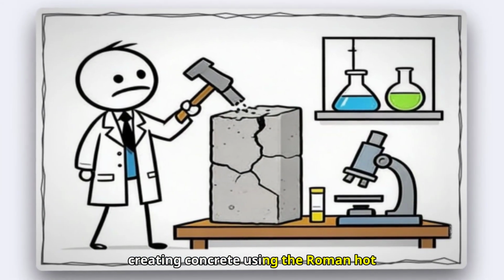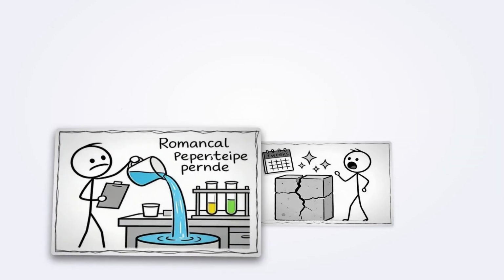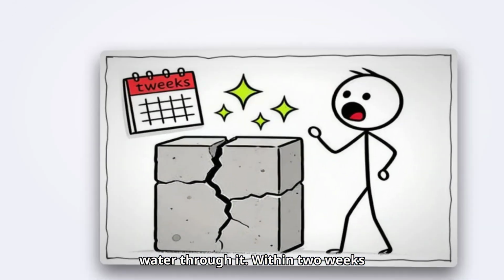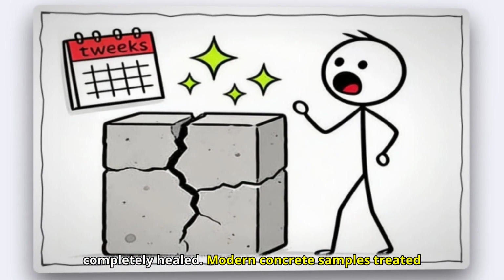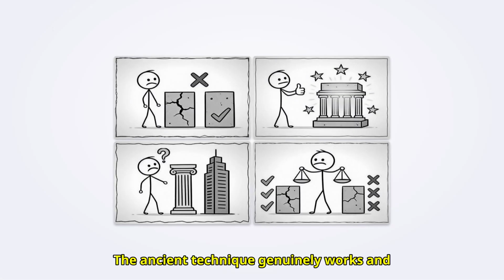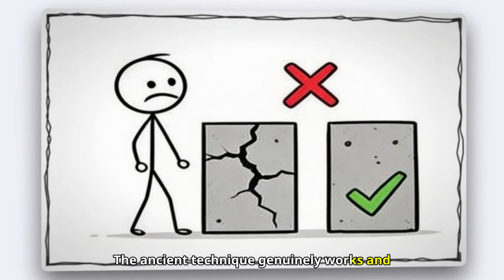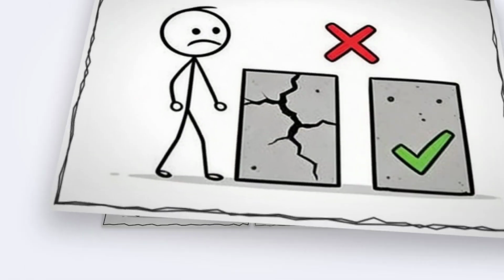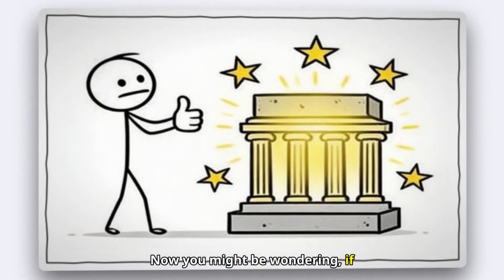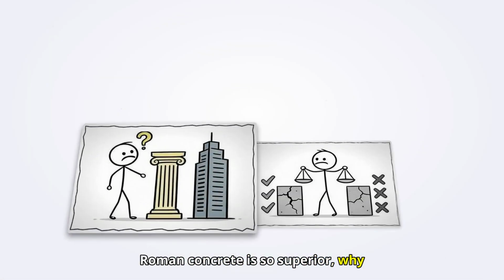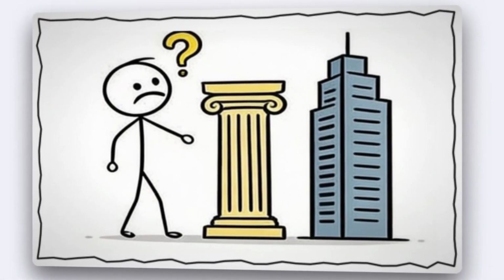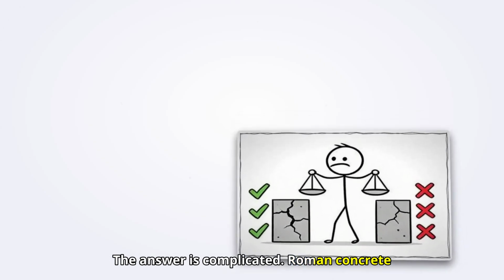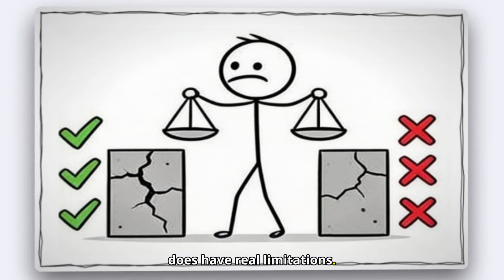The MIT researchers tested this by creating concrete using the Roman hot mixing technique, then deliberately cracking it and running water through it. Within 2 weeks, the cracks had completely healed. Modern concrete samples treated the same way showed no healing at all. The ancient technique genuinely works, and it works remarkably well. Now you might be wondering, if Roman concrete is so superior, why don't we just use it? The answer is complicated. Roman concrete does have real limitations.